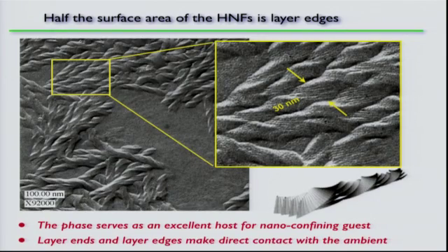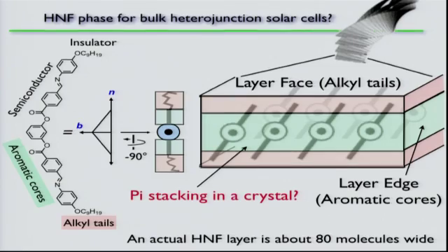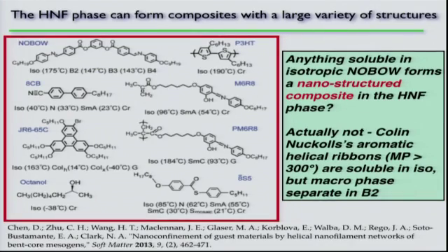And so half the surface area of these helical nanofilaments is edges of layers. And we've got this organic semiconductor where we have this semiconductor aromatic crystal, and then we have these tails that are insulator, and the crystals are making direct contact with the ambient at the ends of the layers and at the edges of all the layers. And we have this way of making composites with helical nanofilaments. All these things, and also solubilized fullerene. C60 won't go in. That's one of the few things that won't go in. But PCBM, which is a solubilized C60, will go in and make a 50% by volume nanostructured composite.